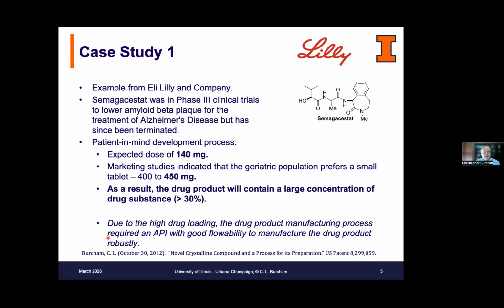And this is work I did many years ago when I was at Lilly and published a couple of times. We had a project for Alzheimer's that was in very late phase clinical trials, subsequently terminated. But as we were moving rapidly through phase 2 into phase 3, we had a problem statement where the dose was expected to be quite high, on the order of 140 milligrams, and the tablet needed to be quite small for the geriatric population that it would be serving, so 400 to 450 milligrams.